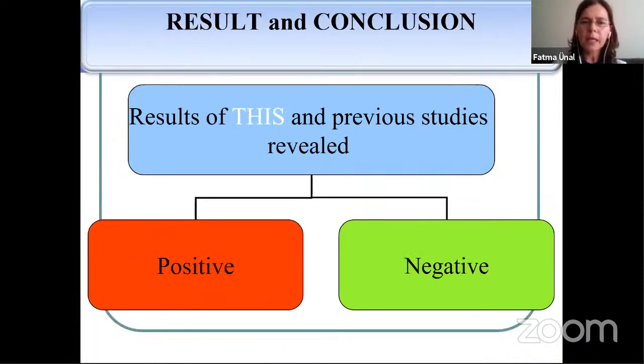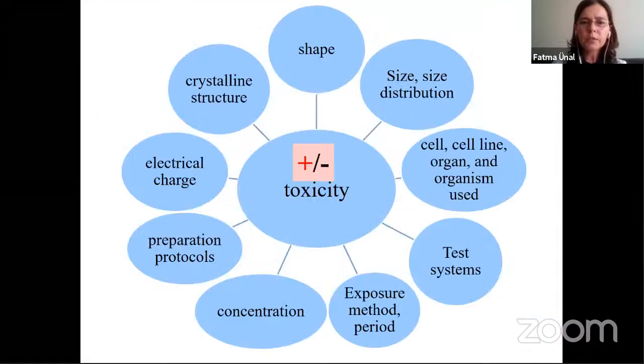The results of these and previous studies revealed that nanoparticles have both positive and negative effects in cells. These differences may be due to differences in the shape, size and size distribution, crystalline structure, and electrical charge of the nanoparticles. In addition, cell line, organs, and organisms used, test systems, exposure method and period, concentration, and preparation protocols are also important parameters changing the effect of genotoxicity of nanoparticles.